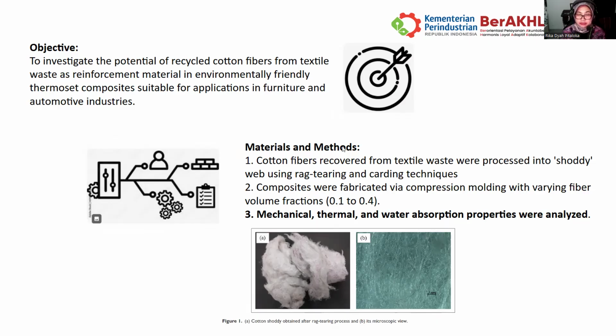We have the material and methods here. First, as explained in the previous slide, the cotton fiber is recovered from the textile waste and then processed into shoddy, making the shoddy web using rag tearing and carding techniques. After that, the composites were fabricated via compression molding with varying fiber volume fraction, from 0.1 up to 0.4. Lastly, we will analyze the mechanical properties, thermal properties, and also water absorption.